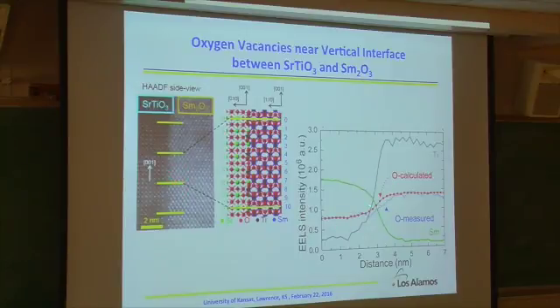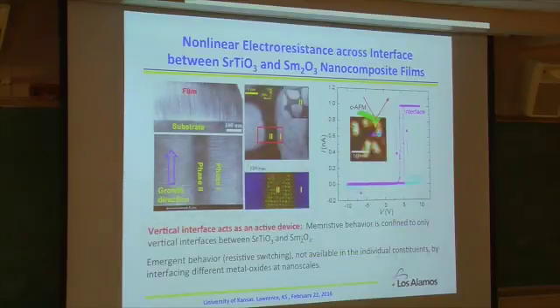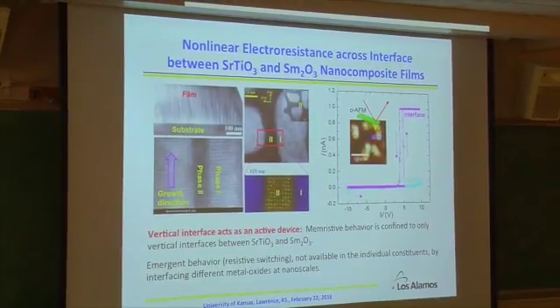Then we do this EELS and look at the chemical information. The interesting thing over here is really the oxygen. Right across the interface, you have oxygen deficiency. Well, can you use this kind of thing to do something or not? Actually, it's very, very interesting. We found out when you do like a conductive AFM, okay?